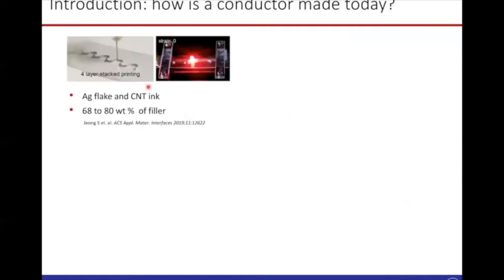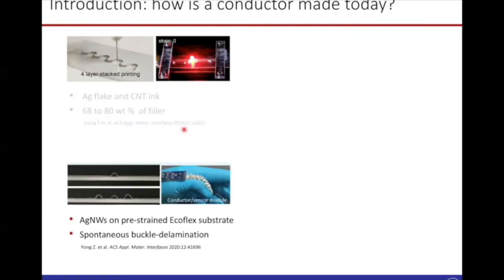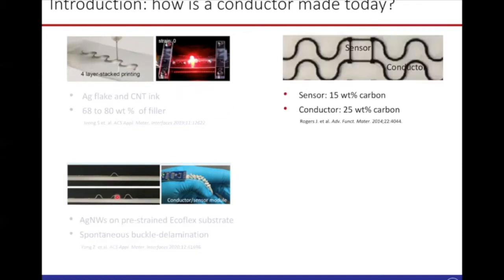Now here a group of researchers are trying to make a stretchable conductor using Ag flakes and CNT with a filler concentration of around 80%. So by increasing filler concentration and sometimes using some surfactants to have better binding, you can increase the conductivity. And here is another group of researchers trying to develop a stretchable conductor by engineering the structure. So having a buckled structure, you will somehow reduce the strain on the non-conducting part. And as a result, you can minimize the change in resistance. Here is another group of people. They were trying to develop a sensor and conductor. On the sensor, you have a straight line, and on the conductor, you have a serpentine-like structure. In that way, you can minimize strain on the conductor part.